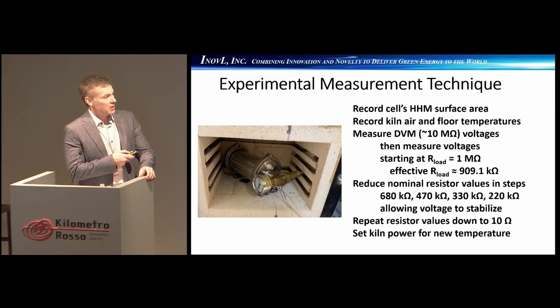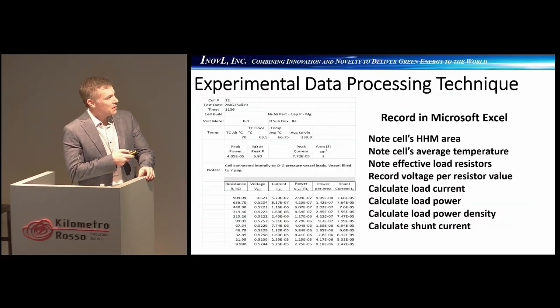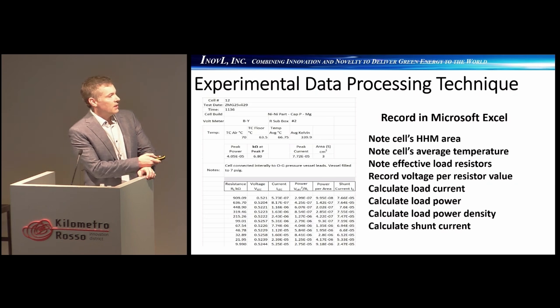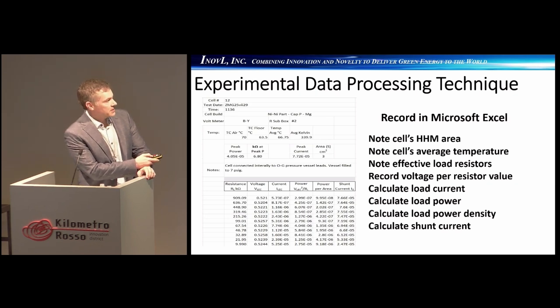And so you start from 1 megohm and step down. And you go all the way down to 10 ohms. And you record your data and decide what new power level you'd like to go to and what temperature, and wash, rinse, repeat. After you do your testing and collect your data, this is what I call our first look data processing, where we record the cell number, the date, the time the test was run, what was the build of that cell, what equipment we were using to test it with, and then we just record our voltages versus resistance, and then do some basic calculations of the current, the power per area, and our shunt current.